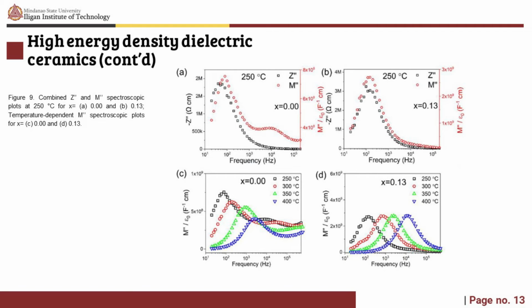So figure 9 shows the combined Z and M spectroscopy plot at 250 degrees Celsius for x, where in A it is 0.00 and in B it is 0.13, and the temperature dependent M spectroscopic plot for x equals 0.00 and for x equals 0.13. The electrical microstructure of BF-BT-xBLN is investigated by IS as a function of temperature and frequency. The spectroscopic plot of Z and M at 250 degrees Celsius for BF-BT-xBLN with x equals 0.00 and x equals 0.13 is shown in figure 9.